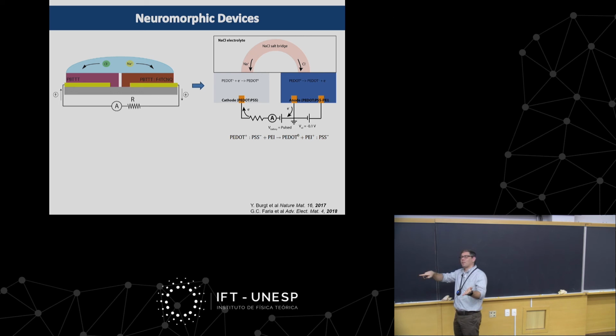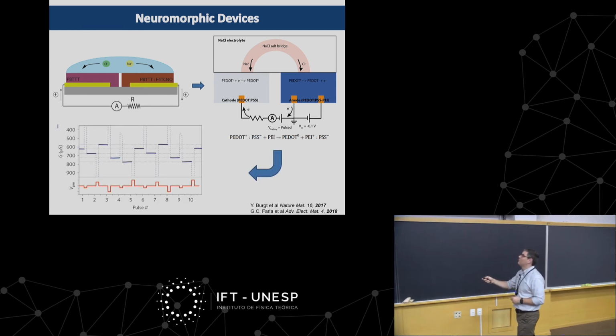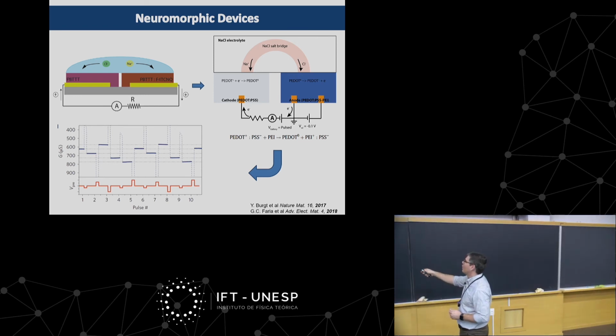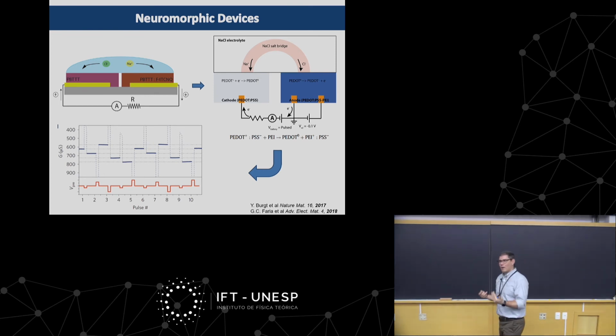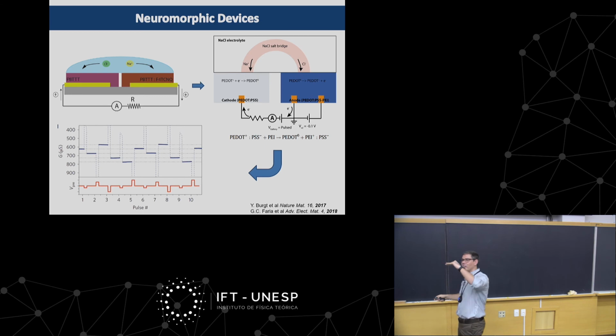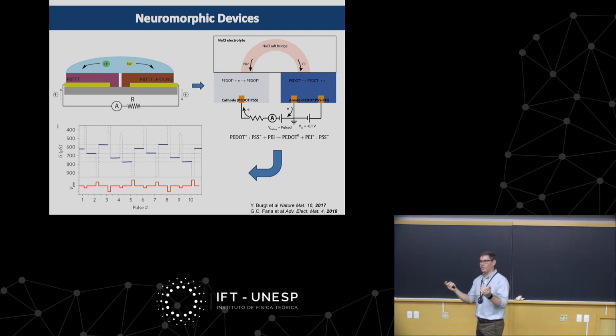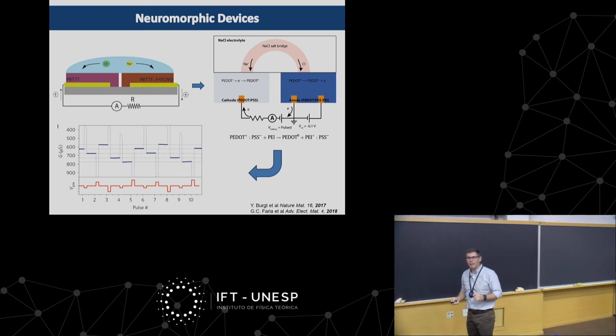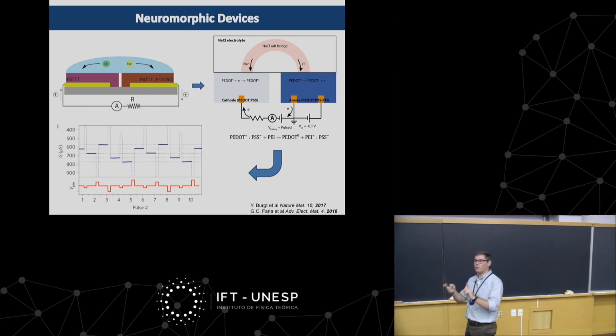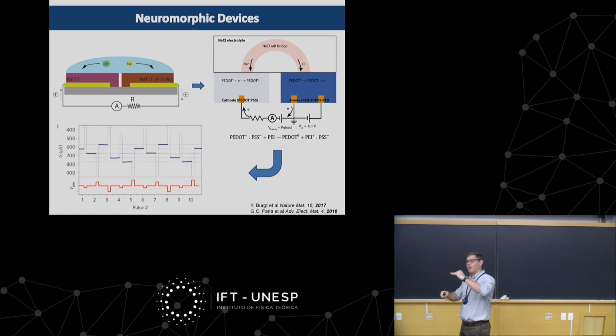If I shut that switch, charges will discharge, and then I move to a different level of memorization. And so I can build, basically, an analog memory similar to this. So I move the state of conductivity to a lower one. The other way around, I can also apply a potential, so I move up or move down, and you see all those states are non-volatile, so they remain for a long time. So basically what I'm doing here is working at different potentiation on one of the electrodes by applying cycles of repeated potential, or opening and closing a switch, like a switch of a light, right? And this could be related to rehearsal because, for a computer, something like a transistor could open and close a gate for discharging, and then I move to different levels of potentiation.